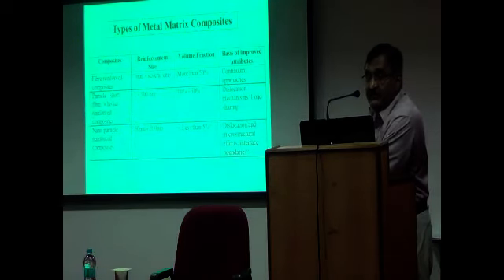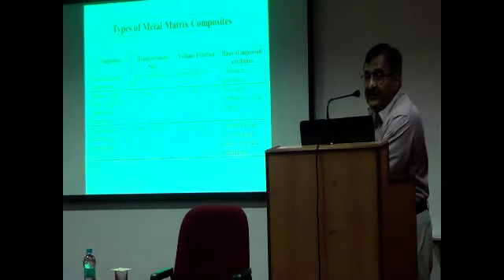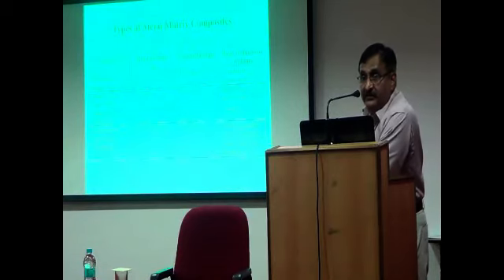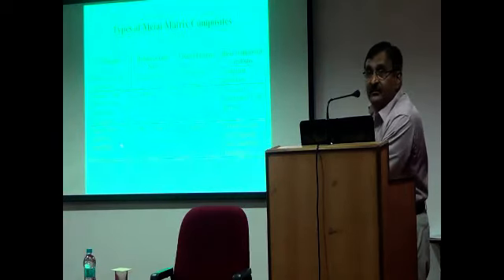If you reduce the size further, instead of a long fiber, instead of coarse particles, if you use the reinforcement at a nano size, you can achieve the properties that you can achieve with a 50% fiber with less than 5%. That is the beauty of these nano size particles, which you can incorporate into a metallic matrix. I'll share with you what the difficulties are. But all the difficulties that were associated with these two classes of materials, both the fiber and the coarse particle, can be overcome using nano size reinforcements in a very small volume fraction. But these materials are on the horizon only in the last 4 or 5 years.